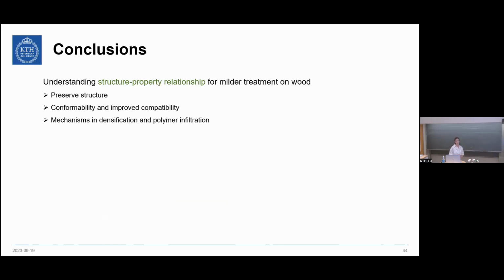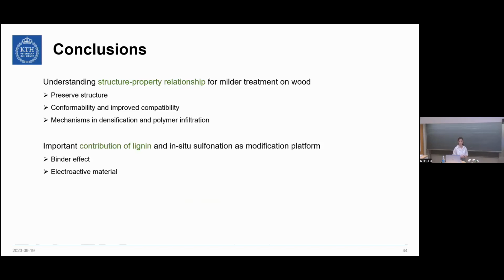So to summarize my thesis work, what we could achieve was a better understanding of the structure-property relationship between different wood modification approaches, and that in most cases it was fundamental to preserve the structure as well as the components as much as possible, while at the same time increasing both the conformability to densification as well as the electrostatic attraction between the wood structure and the conducting polymer. Furthermore, we could see that if we understand the mechanism of both densification as well as polymer infiltration, then we can actually control it while we modify our wood material.